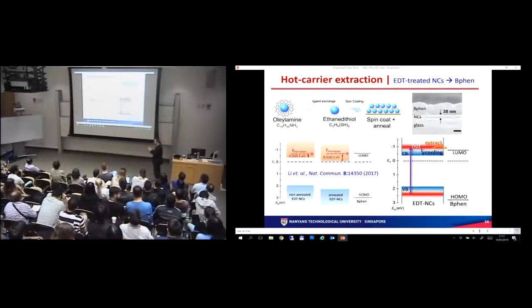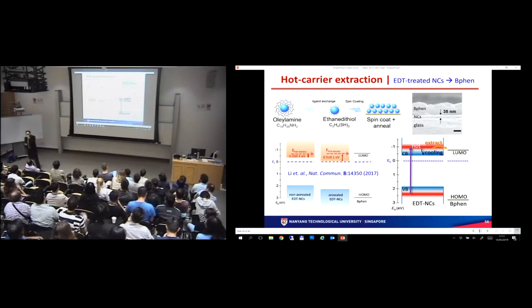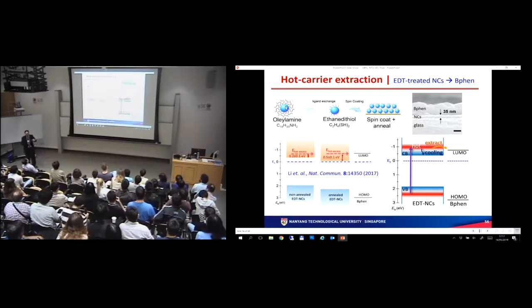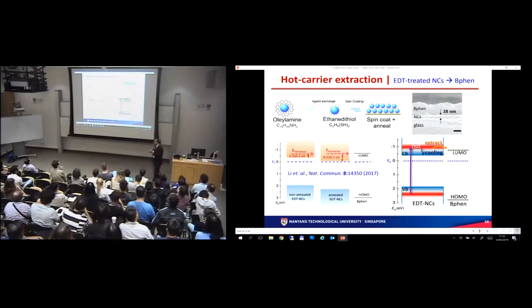Now, I'm going to move on to talk about hot carrier extraction. Yes, we managed to slow down your carrier cooling by going nano. But if you cannot extract the carriers, it's still just a thought experiment. Nothing's going to work. So in this part of the work, we try to extract these hot carriers out. The original quantum dots have very long chain ligands, the oleylamine. We have to do a ligand exchange to shorter ligands, the ethanedithiol (EDT). Then we spin coat them on a substrate, and we interface this perovskite nanocrystal layer with an electron extractor, Bphen, an organic semiconductor. This was determined to align well above your conduction band.